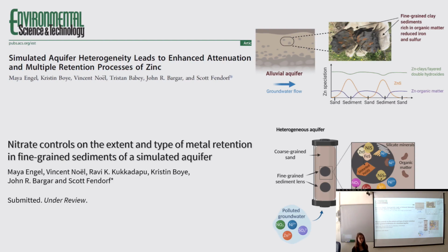So what's the most important about them really is the composition rather than their texture? Would that be correct? Sorry, could you repeat that? What's most important is really their composition, the fact that they're organic rich rather than the fact that they have fine texture? I think it's definitely a combination of both. You need the organic matter there for the activity of the bacteria that are sustaining the reducing conditions. You can't take those apart. Okay. My question really would be if you put, say, silt or clay without any organic matter, presumably you wouldn't have the same effect. No, I mean, you'd still probably have preferential accumulation of the metals because of the interactions, specifically with the clays, but you probably wouldn't see the impact of the redox environment.